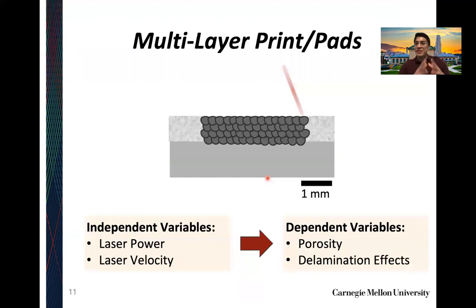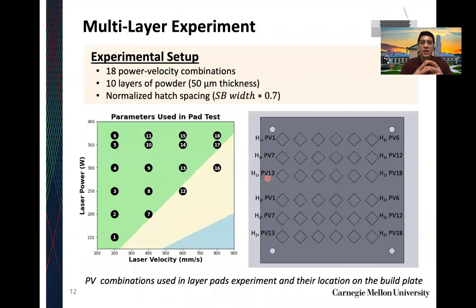So we found a zone where we can essentially use the laser power and laser velocity and be guaranteed full melting. And we worked with that and leveraged it to start to build up pads. And from there, we wanted to evaluate the porosity as well as observe any delamination effects between the pad itself and the substrate. We used 18 power velocity combinations. As you see on the left here, most of these combinations are in the acceptable or full melting region of the single beads. But a couple of them we decided to do in the partial melting just for the sake of experimentation and see how porous parts we would get there.